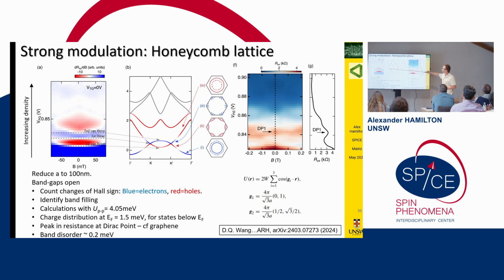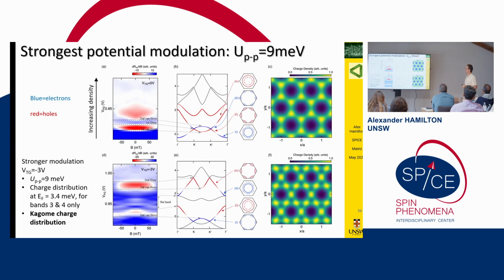But wouldn't it be nice if we could make this band flat and maybe do some flat band physics? And so to do that, we need to increase the modulation strength. That's just a matter of increasing the gate voltage. We can do that. So we increase the gate voltage. The peak-to-peak modulation goes from 4 millielectron volts to 9 millielectron volts. And if we don't look at these two bands, because nothing interesting is happening here, we want to see what's happening with the flat band.